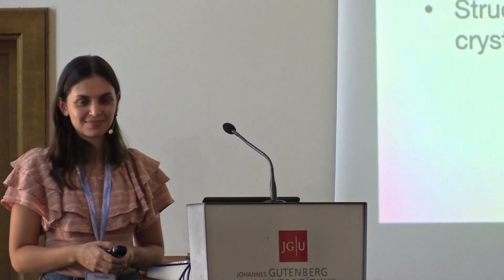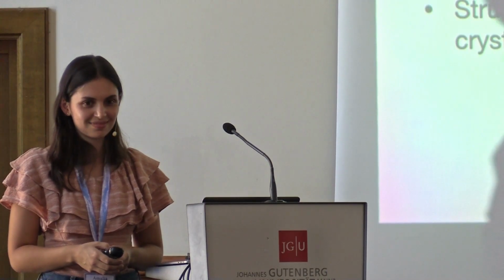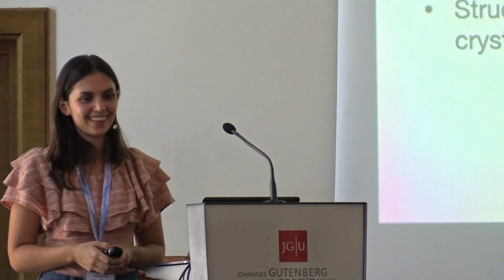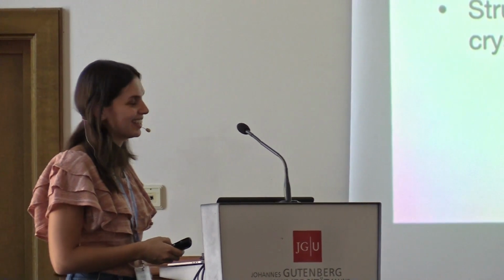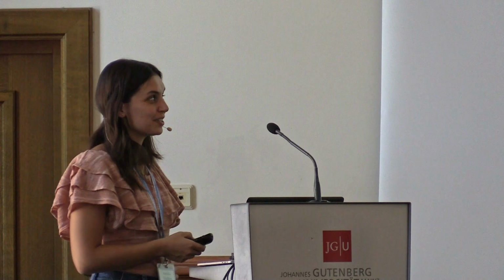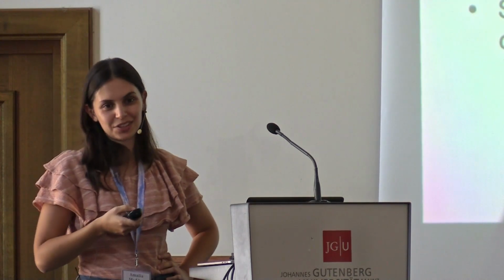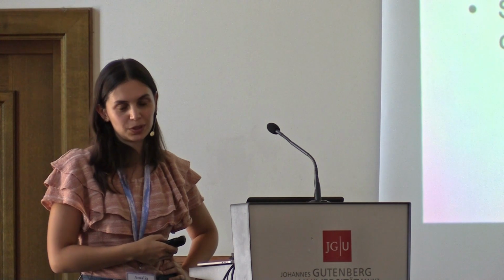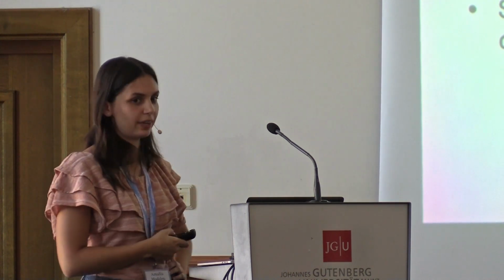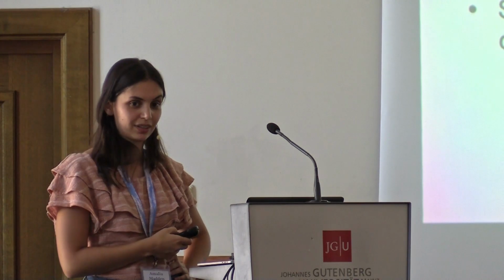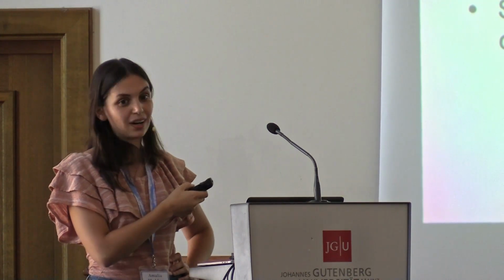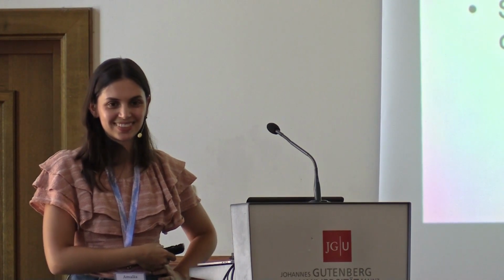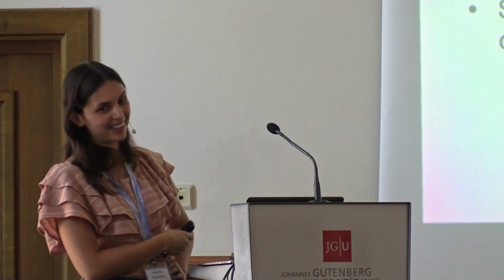The first question is about the material. The best material for that must be ferroelectric. I can see the list there. There are a lot of ferroelectrics, but the clean ferroelectrics must be the best choice. There's an issue with ferroelectrics, which is that because of their domain structure, they would probably have a lower quality factor. It's better to find a piezoelectric crystal that's not ferroelectric. However, for our follow-up paper, we are considering ferroelectric materials. But piezoelectricity is because of ferroelectricity? No, all ferroelectrics are piezoelectrics, but the opposite is not true.